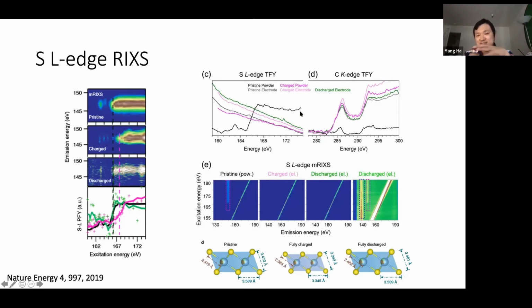But when you make it an electrode, you have to mix in a lot of carbon. And at our beamline, when you have a lot of carbon mixed in, the signal is going to be dominated by the second order carbon, and you really can't see any sulfur signal. But if you look at the RIXS map, here we can see the carbon emission and the sulfur emission here. And we can just focus on the sulfur emission, doing a partial fluorescence yield.